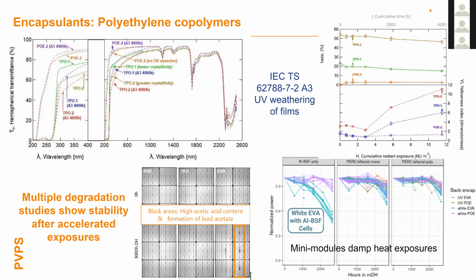So what this tells us is that the degradation of this white EVA encapsulant actually caused much more degradation to the ALBSF cells than the PERC cells. There's material compatibility things we need to account for when building up our whole PV system, since some materials might work better with different cell types. This white EVA was causing degradation due to the TiO2. If it's not a high quality TiO2, rutile TiO2 actually becomes a radical and starts attacking the polymer backbone, causing, in this case, much more acetic acid formation.